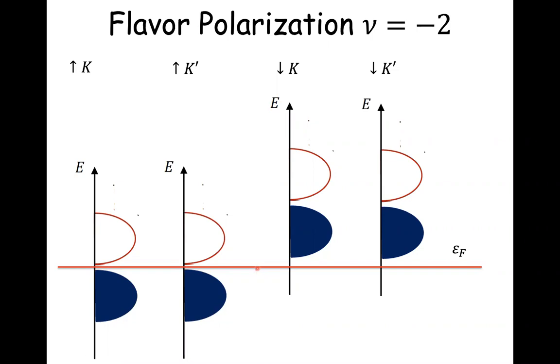But the thing that's different when you have the Moire superlattice is that you can also put the Fermi level in a gap by, for some spin and valley, completely emptying the flat bands or completely occupying the flat bands. And because the flat bands are so narrow, as I've showed you before, it turns out you can easily do this and break these symmetries and have different filling factors for different flavors. And so in this way, you can easily get a net Hall conductivity.